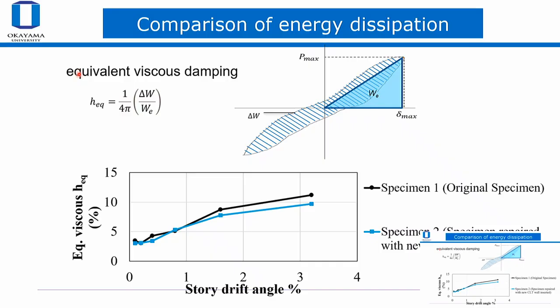One thing is energy dissipation. For both of the specimens, we calculated energy dissipation using equivalent viscous damping, calculating the energy inside each loop and comparing it to the potential energy. I think maybe you have already seen that concept in some places. This is the original specimen, the black one, and that's the other one. If you see here, it starts with 3%, and then it goes up to 10%. Usually RC walls are a little bit higher than 3%, usually 5% or so. I think the energy dissipation of CLT is less than RC walls because it doesn't have much cracking. But I think the energy dissipation was good as well.